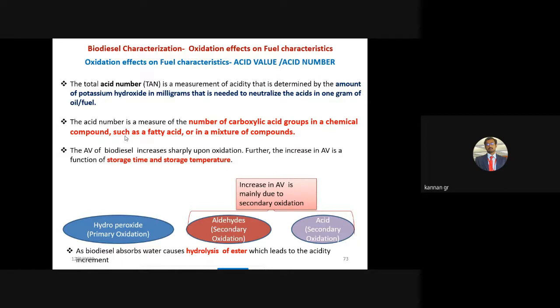So the acid value of biodiesel increases sharply upon oxidation, with further increase due to storage time and storage temperature. But the primary oxidation, the hydroperoxide, is formed inside the biodiesel once it is exposed to the atmosphere, once water is present in it, or through thermal treatment. The increase in acid value is mainly due to secondary oxidation. After hydroperoxide formation, aldehyde and acid formation takes place inside the biodiesel. That leads to an increase in the acid value. Once the acid value increases, what will happen? It will affect the whole fuel supplying system.